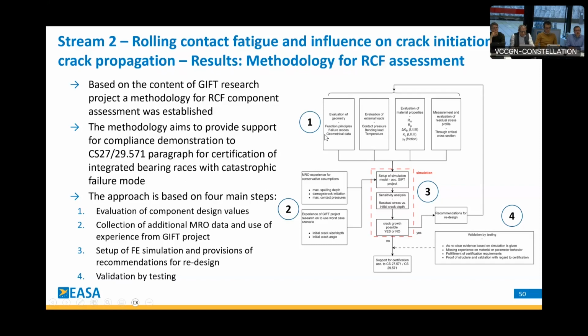Step 1 is the evaluation of component design values. It's the geometry, function principles, known failure modes, geometric data. Evaluation of external loads, for example, contact pressure, bearing loads, temperatures. Material properties, also of course related to crack propagation and crack initiation, next to the standard material values. And of course, measurement and evaluation of the residual stress profile, since this is the baseline data of a component that you want to use, that you want to design, that you want to reuse, whatever.